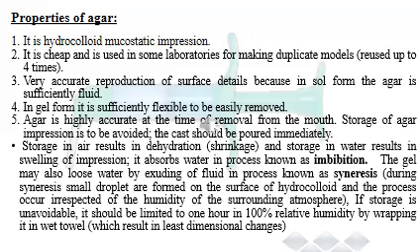Storage of agar impressions is to be avoided. The cast should be poured immediately. Storage in air results in dehydration and shrinkage, and storage in water results in swelling of the impression. It absorbs water in a process known as imbibition. The gel may also lose water by exuding fluid in a process known as syneresis.